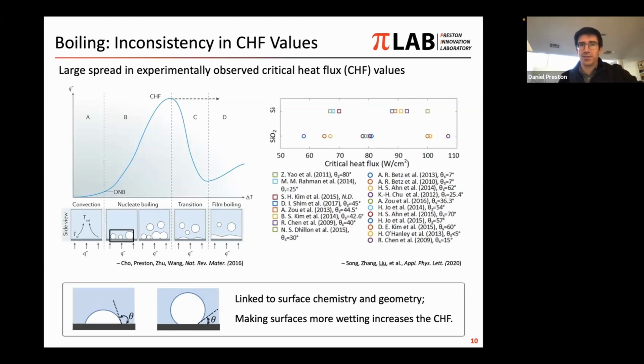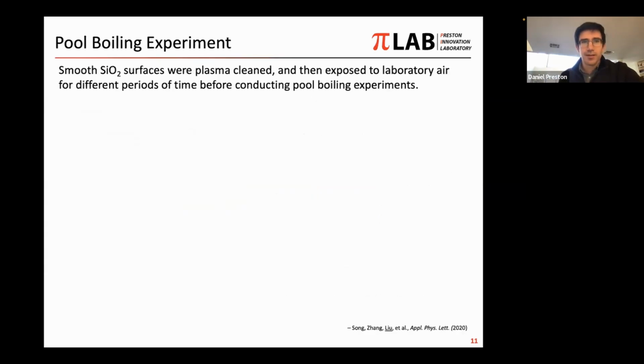But we find out that, for example, in this paper, looking at just the literature regarding silicon and silicon dioxide, that the reported critical heat flux values, even when these surfaces are nominally flat, are all over the place. They vary by maybe 50% or more. And so there's a lot of disagreement in the literature on what is the critical heat flux value on these surfaces. And so we've conducted some work here to try to understand or explain why that might be. In this case, we took some smooth silicon dioxide surfaces, we plasma cleaned them and exposed them to lab air for different periods of time, and then did pool boiling experiments.